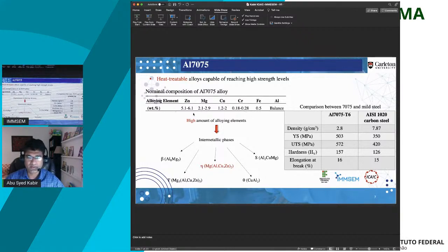The chemical composition shows that it has about 5 to 6% zinc, 2 to 3% magnesium, and about 1.2 to 2% copper.